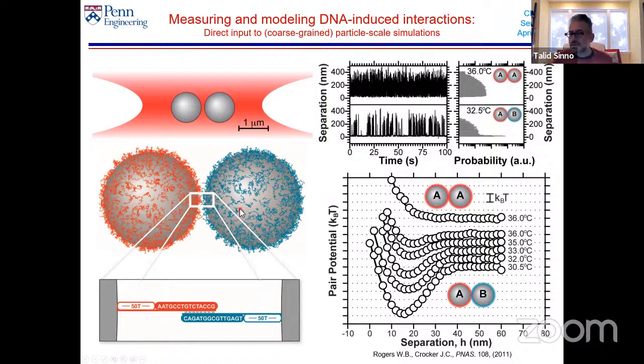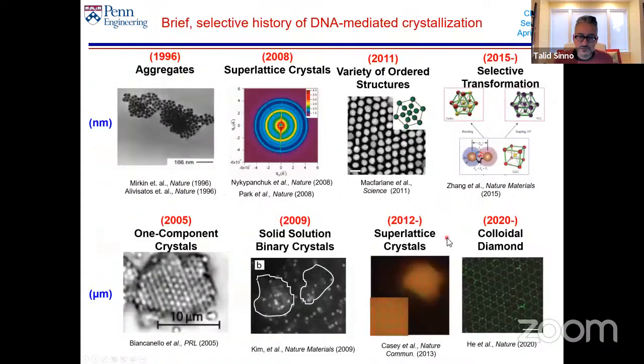The other subtle detail here is that the extent of hybridization at a fixed separation between these two particles is very much temperature dependent. So you can go from having rather strong attraction to weak attraction over a rather small temperature range. This is built into the potential that we feed our simulations. We take this information and pass it into either a molecular dynamics simulation, a Brownian dynamics simulation, or even a Monte Carlo simulation, and we use this to run things.